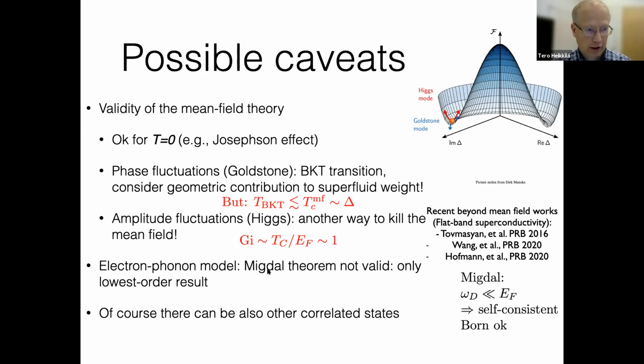Okay, and then another caveat is this failure of the Migdal theorem, which basically states that you can do the self-consistent Born approximation for electron-phonon, but actually for low order, in the lowest order, this is okay. And another caveat is that I only consider the superconducting state, but actually there could be also other types of correlated states, which is what has been seen in twisted bilayer graphene.